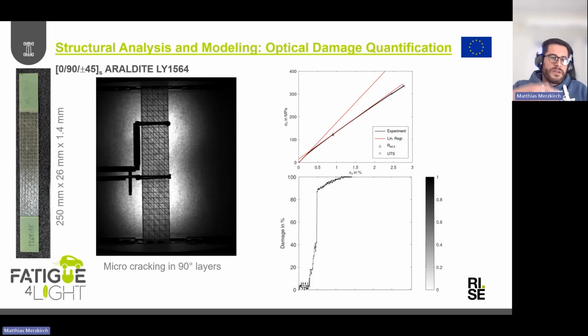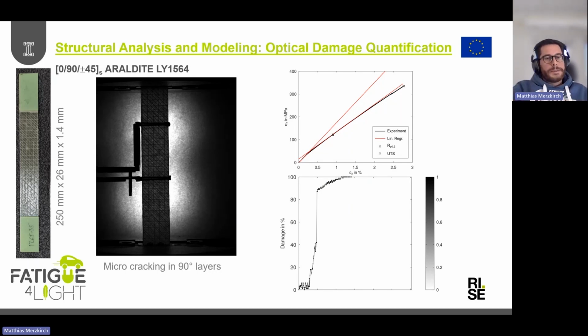In that case, we see the stress-strain curve determined. And what we see through this 1.4 millimeter thick specimen is that it's getting darker. This is an effect of the microcracks, especially in the 90-degree layers in between the fibers. That's one way of characterizing damage. The darker it gets, the more damaged it is. And already at very low strain levels, around 0.5%, we see a drastic increase here.